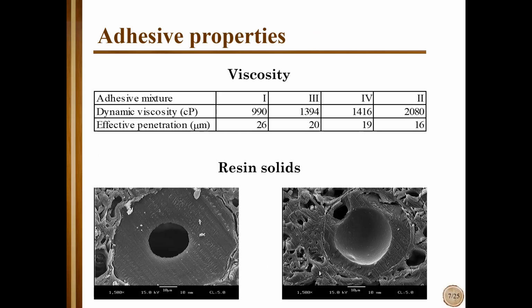Some details on how viscosity impacts effective penetration. So if viscosity increases, so it's less fluid, normally it means that adhesive will penetrate less. So you can clearly see in this table that with higher viscosity, effective penetration decreases. Also, resin solids is important, because more solids, less mobility, less fluidity. So it's more difficult for adhesive to penetrate. Molecular mass or molecular weight distribution is also very important. Small molecules can easily penetrate into wood, big molecules not.